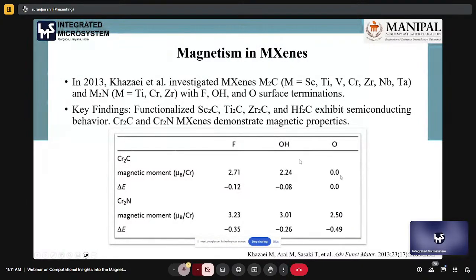So there is no magnetic moment. The energy difference between the ferromagnetic and antiferromagnetic states is 0. And for nitride, they got magnetic behavior for all three terminations, fluorine, hydroxyl, and oxygen. That means the surface termination is a very important parameter here. As you can see, with chromium carbide we see 0 magnetic moment when we terminate with oxygen, but in chromium nitride we got a magnetic moment of 2.50. So we have tunability based on the surface termination, meaning which atom we terminate the surface with plays a very important role in the magnetic properties.